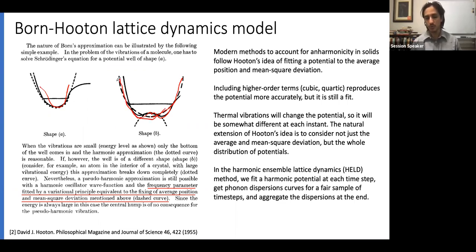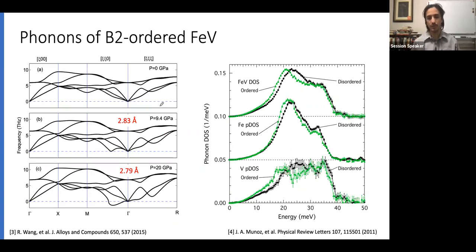Most models nowadays find the parameter that is the best fit to this approximate parabola. They might have higher order terms like cubic and quartic, so that makes the fit better, but it is still a fit. What we're doing instead is to look at the potential at different time steps. At each time step, it looks a little bit different, and so we get force constants and dispersions from that. The dispersions might look a little bit funky at a given snapshot, but by aggregating all of them, we recover the correct dispersions and they actually have a broadening.